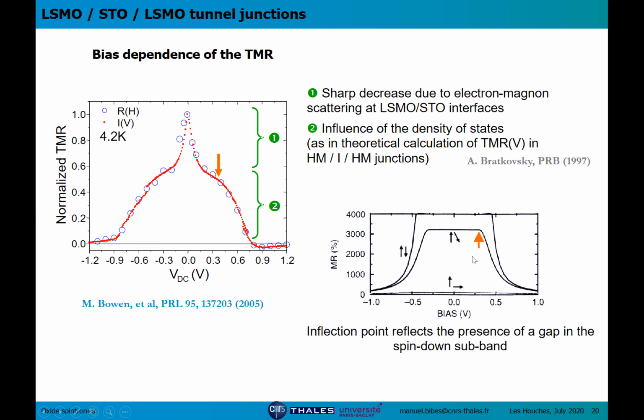This plateau was predicted in this paper by Bratkovsky, who calculated the bias dependence of the TMR in junctions using half metals. Maybe I forgot to say that if you have a perfect half metal with 100% spin polarization, you should expect infinite TMR at zero bias. So you should get millions and billions of percents. Effectively, it's never like that because you never have a perfect half metal.